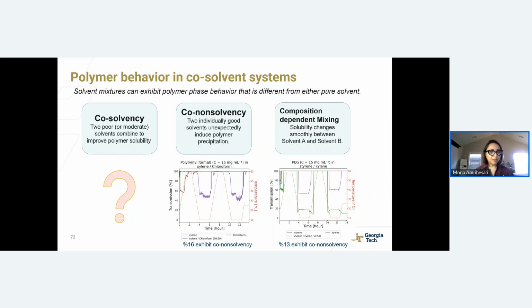Out of these experiments, 16% exhibit co-non-solvency, as in this example of polyvinyl formal, xylene, and chloroform. So we had this unique behavior of the polymer being soluble in both of these solvents, xylene and chloroform, in 1 milliliter of each, and then we mixed 50-50, and we saw non-solvency happening, meaning that the transmissivity dropped to a lower value.